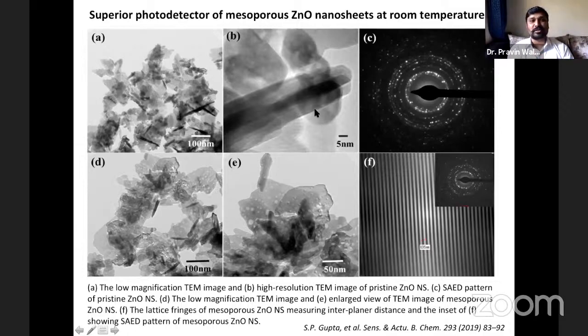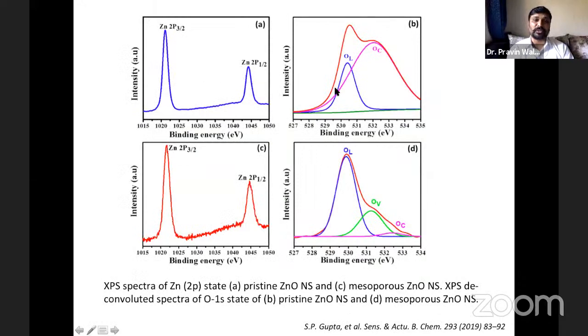So we have tried to check whether this normal zinc oxide sheet, or non-porous zinc oxide sheet as synthesized, and this annealed mesoporous zinc oxide nanosheet, what is the difference between them? Okay, so before going to see those differences, we have just done the XPS measurements on both the samples, normal pristine zinc oxide and mesoporous zinc oxide. So here in both cases, we have found the zinc 2p3/2 and 2p1/2 peaks, 2 peaks. But here in the oxygen, especially, we are very much interested because zinc has adsorbed oxygen on the surface, but here this OL is the lattice oxygen peak we have observed, right?